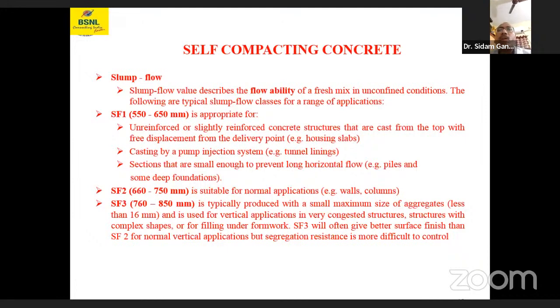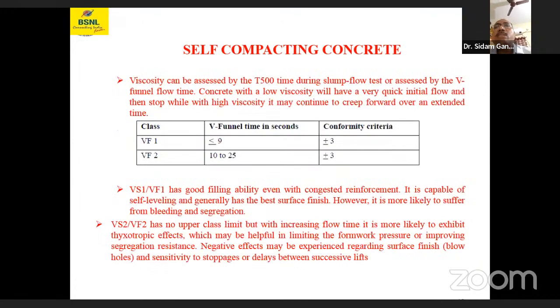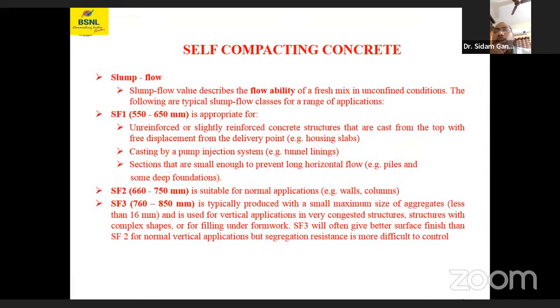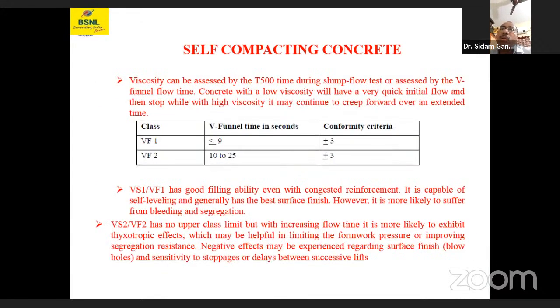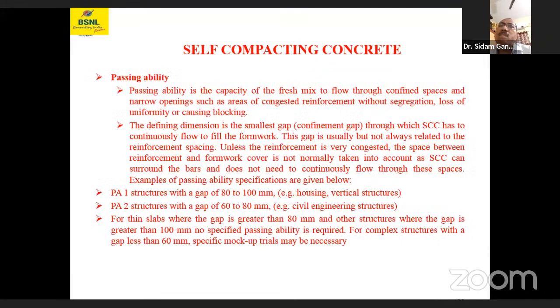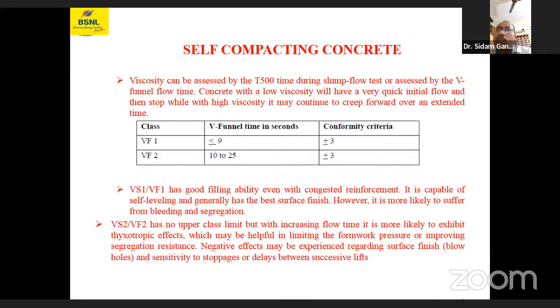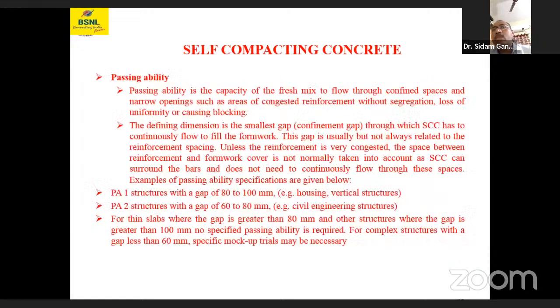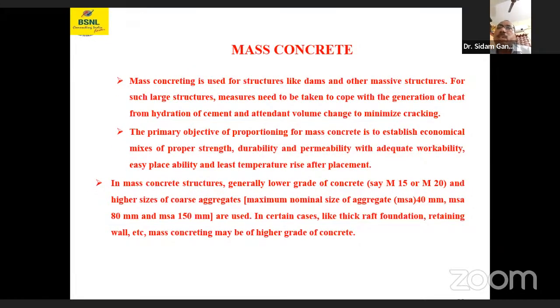So M30 and above, cementitious content is 400 to 600. Here I want to mention cementitious content. As per IS 456, the quantity of cement is restricted to only 450. But here, cementitious content means you can restrict cement to 450, and the remaining 150 you can add as GGBS. So that also we have to fulfill the codal provisions. Otherwise, for M30, 400 is not advisable. It is very expensive. So when we design the mix, we have to think about the cost of the concrete also.